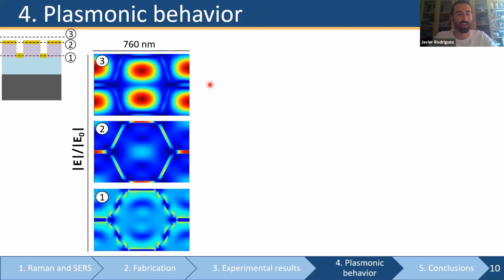And we wanted to probe 3 different planes of this structure, always by simulation, I insist. These 3 planes were the positive honeycomb structure, what you can see here. It stands for this image here. The negative honeycomb structure, where everything is gold and you have air in these trenches that you can see here. So the field is consistent with this distribution. It's mainly concentrated in the trenches. And we also wanted to see what was happening right above the structure, because in the end, if we want to functionalize this structure with a molecule that we want to detect, those molecules are going to be sitting mainly on this plane here. So this number 3 is the electric field distribution 20 nanometers above the structure.